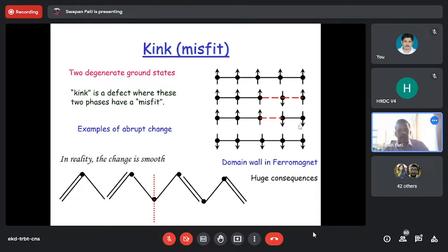For example, as you know, iron is a ferromagnet. And you know what a TC is? TC is 1040 Kelvin for iron. That means below 1040 Kelvin, it should be a ferromagnet. But you try to bring in a pin, does it attract? It does not attract. But take this ferromagnet, an iron ball, and hit it on the ground, same place, quite a few times. You will find near where you are hitting, bring a small pin, you will see it will attract for some time. Then again it goes off.